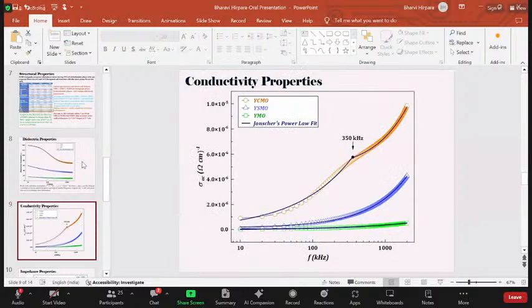Now we move on to the conductivity properties. Here the frequency dependence of AC conductivity is shown. We can observe an enhancement in AC conductivity with increase in frequency. This can be understood as, when an AC electric field is applied, free charge carriers obtain higher energy, and thereby pass across the sample lattices and provide improved conduction. The better conduction can be seen due to the doping of divalent cations at the Y site, which results in transformation of manganese ion valence state from +3 to +4, which helps in a Zener double exchange mechanism based lattice, and that is the reason for the improved conduction.